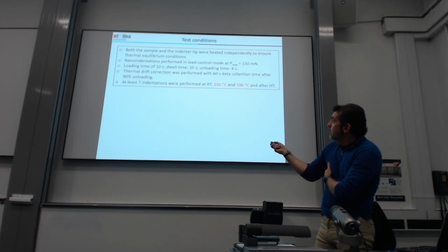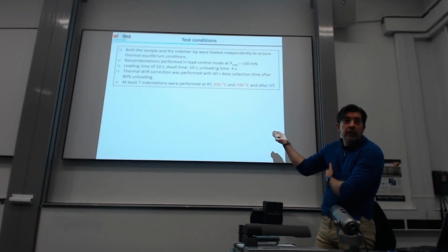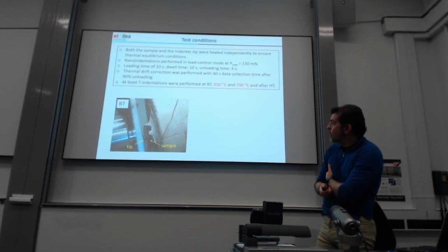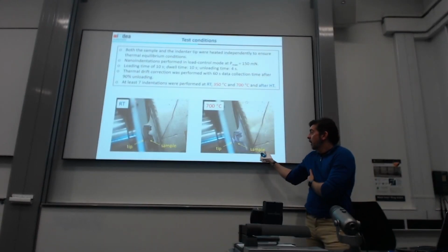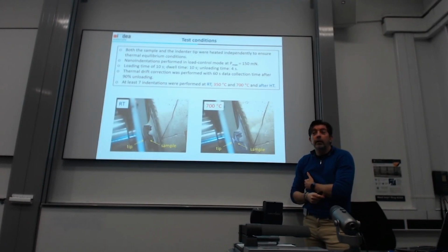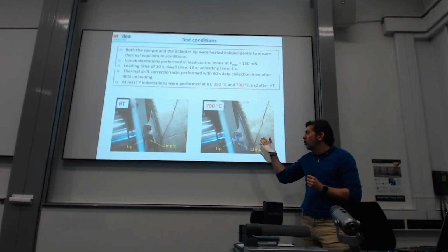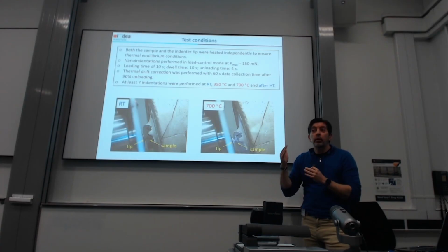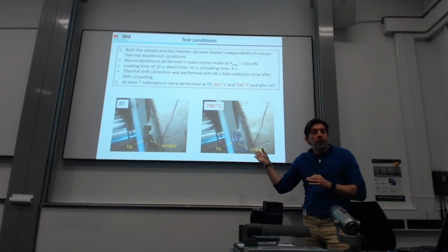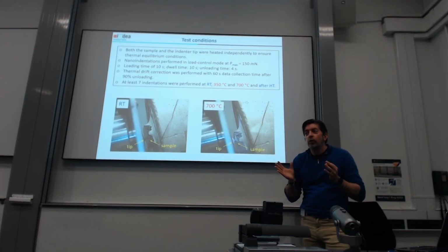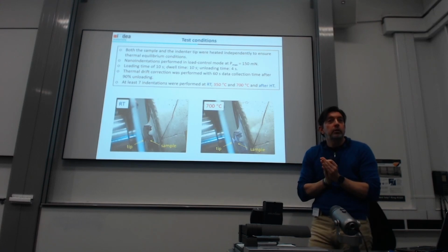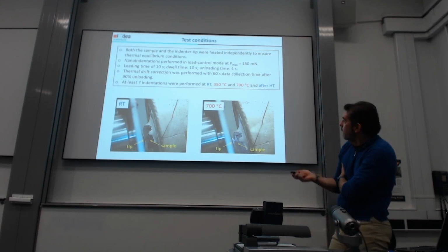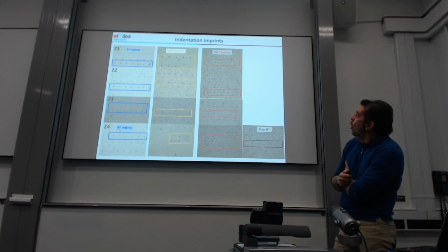At least 7 indentations at room temperature, 350 and 700 degrees. This is room temperature, tip and sample. At 700 degrees, the tip is red hot. It's a cubic boron nitride. It's been used a lot, so I didn't want to push it to 800, just in case. But I thought 700 is already a nice temperature to test these alloys. Some indents, there are no obvious signs of